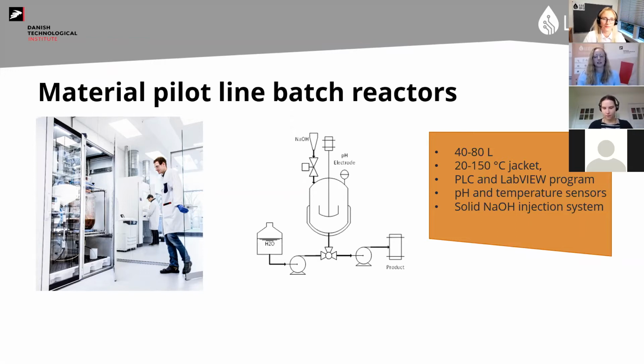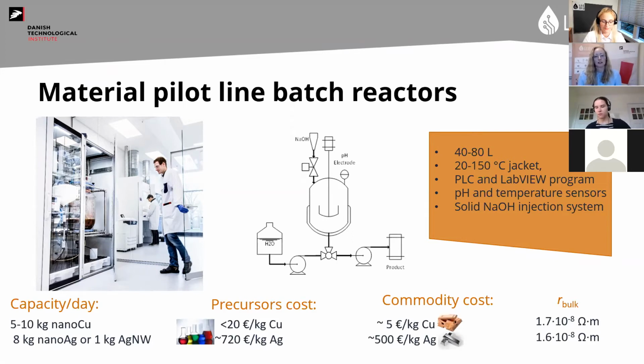This method is really good for producing a lot of material, because you can have really high concentrations of material per synthesis in these. What we usually make in these reactors is silver or copper nanoparticles or silver wires. As you can see at the bottom, the capacity of this reactor right now is 5 to 10 kilos of copper nanoparticles, 8 kilos of silver nanoparticles, and then we can produce 1 kilo of silver nanowires as well. And we're quite interested in the copper development, because if we can replace some of the silver, we can reduce a lot of the process cost. As you can see at the bottom, both the precursor and the commodity cost are quite high for silver compared to copper.